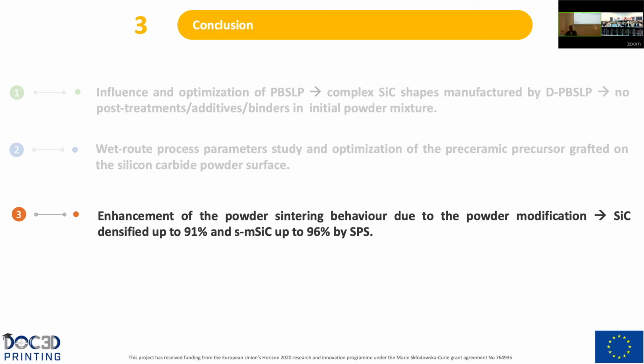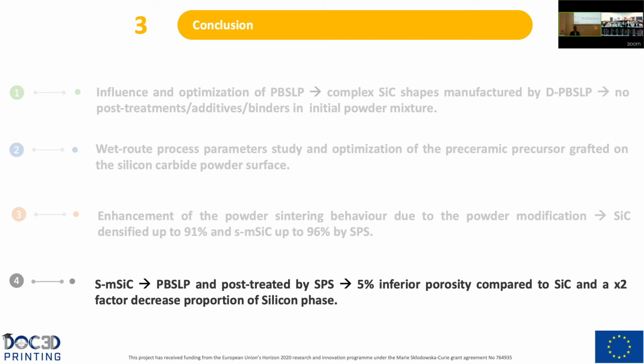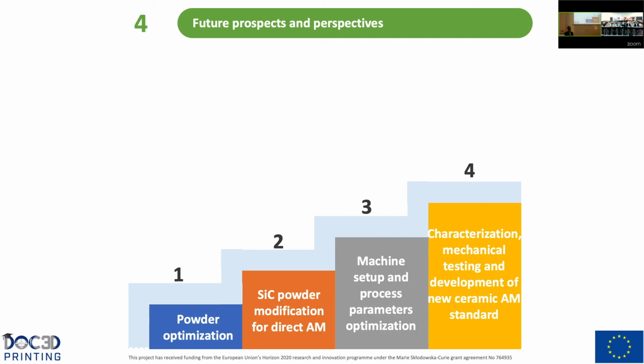For this, we use spark plasma sintering to densify up to 91% the silicon carbide powder and up to 96% the surface modified silicon carbide by spark plasma sintering with the same conditions. And finally, we have manufactured surface modified silicon carbide by powder bed laser processing, post-treated by spark plasma sintering, obtaining a 5% inferior porosity compared to silicon carbide and a 2-factor decreased proportion of silicon phase, because remember we are decreasing the energy density.